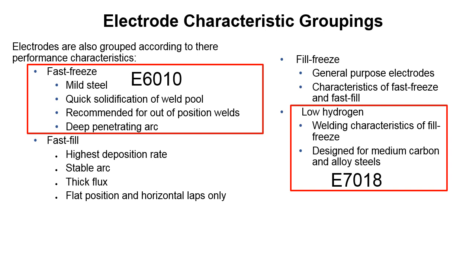Quick solidification of the weld pool. Like with 6010, you run it with a whip motion, a whip and pause. So you get out of the weld puddle, you let it freeze, and you come back in. Get out of the weld pool, come back in, let it freeze. So it's like a magic quick drying concrete almost. It's amazing how quick that weld pool will solidify for you.